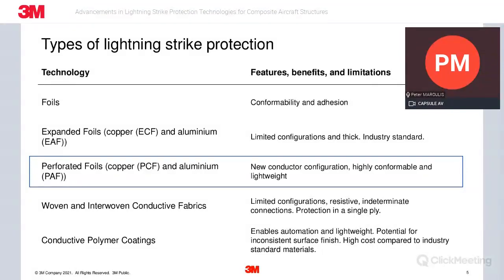And then finally, conductive coatings, which can be applied on the surface by spraying. 3M has done some experimental work in this area in the past. There are some big challenges with these coatings. For instance, ensuring you get enough conductivity with those solutions. Another one is knowing how much material you have applied. And finally, operator consistency is critical. These could all be resolved in some ways, but they are definitely challenges to be aware of.